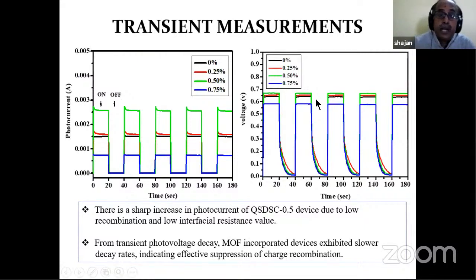This is reflected in the transient measurements that we have made. By using light pulses, we have recorded the time versus photocurrent, how the photocurrent responds to time. And you can see the photocurrent is very high for 0.5%. It is very high. And you can also see the decay. Of course, I cannot show the enlarged one. This one is taking more time to decay. And these are the conditions which favor the increase in the efficiency of the solar cells.